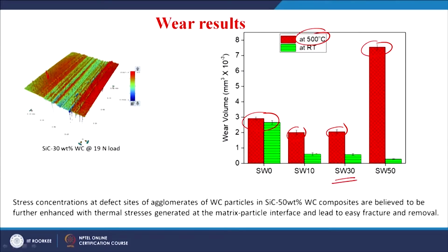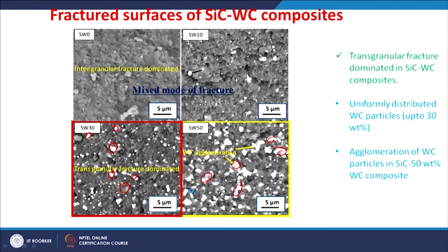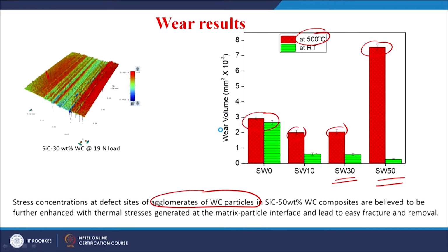But if you look at the SW30 and SW50, the stress concentrations at the defect sites of agglomerates of tungsten carbide particles, which we saw in the previous slide, are dominantly present in the composites with a larger amount of tungsten carbide content. So, these agglomerates result in increased stress concentrations. The stress concentrations at the defect sites of these agglomerates, particularly in the SW50 composite, are believed to be further enhanced with thermal stresses generated at the interface of the matrix and particle. That leads to easy removal of the material. So, you get a much larger wear volume when the tungsten carbide was around 50%.